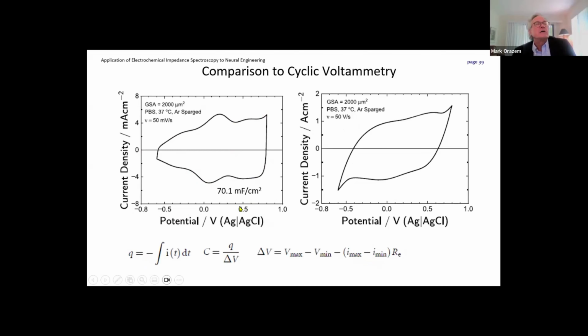So when we do this, we find that for the slower sweep rate, we get about 70 millifarads per centimeter squared, which is quite on the order of what we're getting from our impedance. And if we look at the faster sweep rate, then we're seeing something that's a little bit smaller. The idea is that when we're measuring the impedance, we are capturing the low frequency behavior as well as the high frequency behavior. So it makes sense that the slower sweep rate would be more consistent with what we get from impedance.